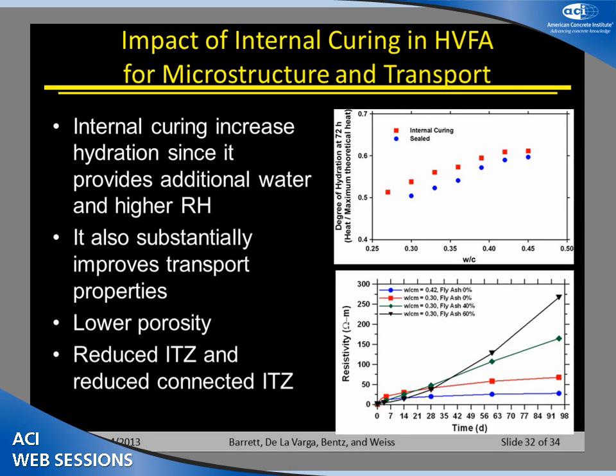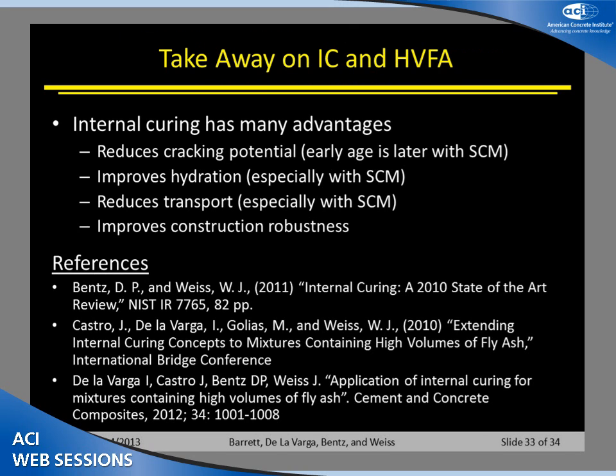The other benefit to this is because we've reduced the water to cement ratio, because we've provided that additional curing, we can see substantial changes in the electrical properties, which mean we've made the system much more dense and much harder to start corroding the overall concrete. So internal curing has a lot of advantages. We can reduce the cracking potential, we can improve the hydration, we can reduce the transport, and one of the other things that I'll mention here very quickly, and I haven't had time to go through it in great detail, but it improves construction robustness because now we're less susceptible to things like thermal shock in the system.